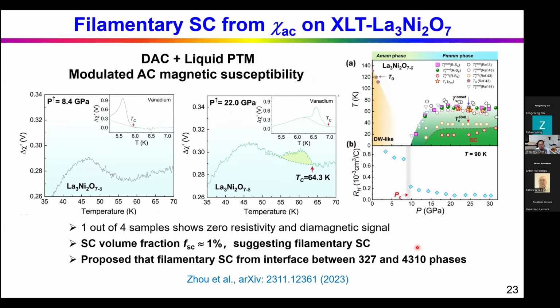It seems to be very difficult. I think Huiqiu Yuan's group also tried to measure AC susceptibility, but it seems to be quite difficult to detect the diamagnetic signal, especially under such high pressures by using a diamond cell. So this is the result from Liling Sun's group.